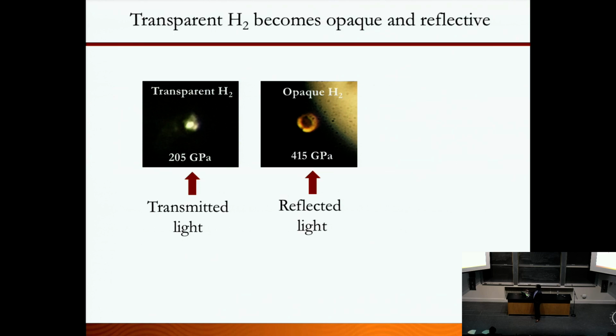What you're seeing right now here, this shiny area, is the gasket that I was talking about. You have two diamonds squeezing each other, and in between you have this metal gasket. In the metal gasket, you drill a hole and you load your sample. If you look from the top view, you will see the circle of rhenium, whatever the gasket material you're using. We were using rhenium. And in the middle, the central area is your pure hydrogen sample. It's opaque. Light doesn't pass through it, indicating something is happening. This is after we saw the new phase.